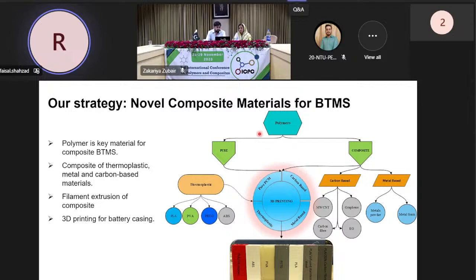So basically we have done that - we have pure and composite materials. We took thermoplastic and mixed it with different carbon-based and metal-based materials. In the carbon-based category, we recently worked on carbon fibers, and also metal powders and metal foams. For thermoplastics, we normally use PLA, PVA, PETG and ABS - these are already easily available and very cheap sources for polymers.